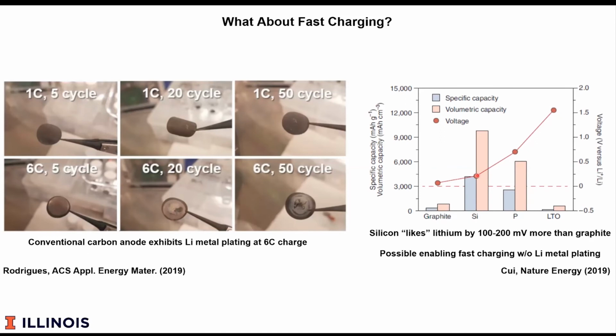So silicon is a little bit, say, the Goldilocks material from the electrochemical driving force. It sits at, say, 100 to 200 millivolts more positive than graphite. So that gives you a substantial driving force that's on the order of many kT versus a few kT. It also has a much higher volumetric and specific capacity, with the key challenge being these large volume changes that the material undergoes.